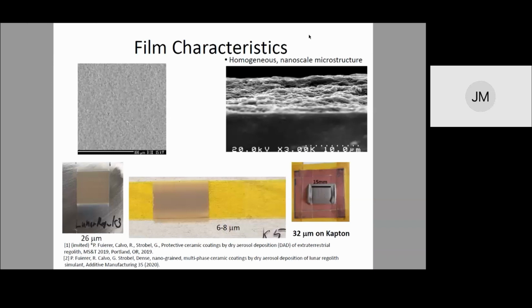And for sake of time, I didn't have the ability to add an AFM image of our films, but the microstructure from those images was around the nanoscale. The bottom three films were sprayed previously by one of my colleagues and co-authors on this project, Robert Calvo. The bottom left is a 26 micron thick film on steel. The middle is on Kapton tape, and the right one is our most recent and thickest film to date, which was 32 microns on 15 mm Kapton. Next slide, please.